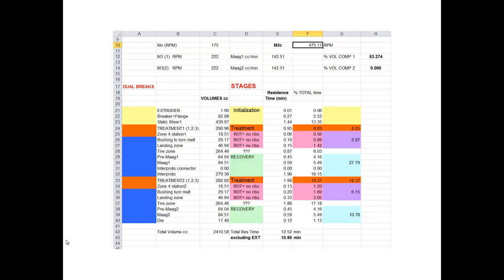So it's another approximately 2 and a half minutes. We have to take that into consideration when looking at the results, because it's important to know that we expect to see and measure a viscosity change while rheofluidification is active. In other words, in the treatment zones. We should see that, and we see it when we measure viscosity from the torque and from the pressure sensors, which are positioned along the flow direction.